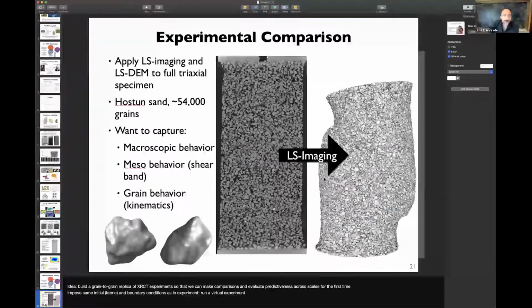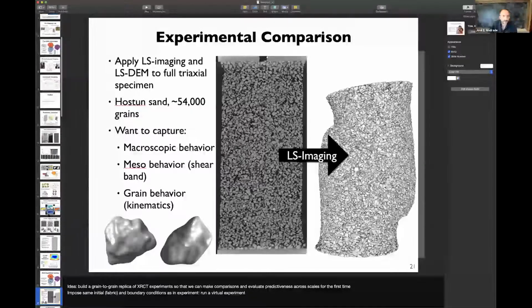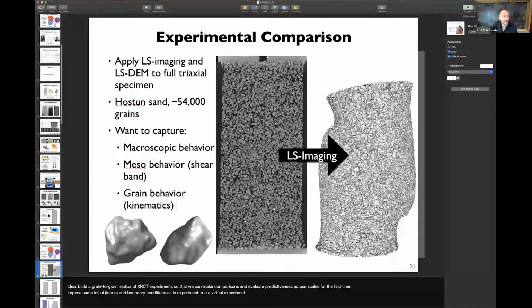And so we go from an X-ray computed tomography of about 60,000 grains, 54,000 grains, and we do a grain-to-grain model of that initial fabric. And so every grain has its avatar in the same shape and location as in the original sample. And then we introduce the same boundary conditions, the same confining pressure, and the same vertical deformation, excuse me, that is imposed in the experiment.